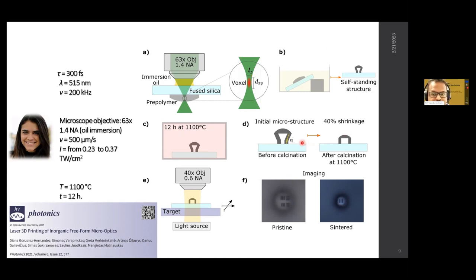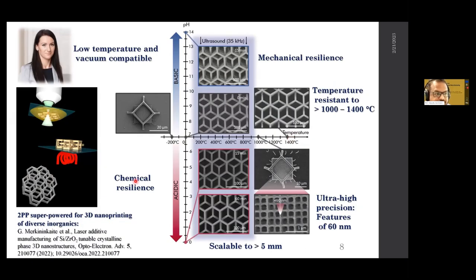The main reason, I would say, is that it's stuck to the substrate, so it cannot move, whereas the upper parts of the object, both the supports and the lens, can shrink, so they do shrink. In the process you have a reduction of mass: the organic parts are evaporated. The carbon and hydrogen, which are a necessity for polymerization, are evaporated, whereas the silicon and the zirconium remain. So we remove around half of the material, which is proportional. It is not shown in this study, but we have research basically dedicated to this phenomenon. So it is shrinking and it's proportional to the organic part. Depending on the heating parameters, we reduce the volume and the dimensions.